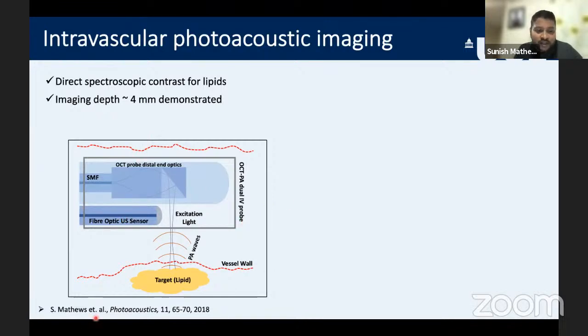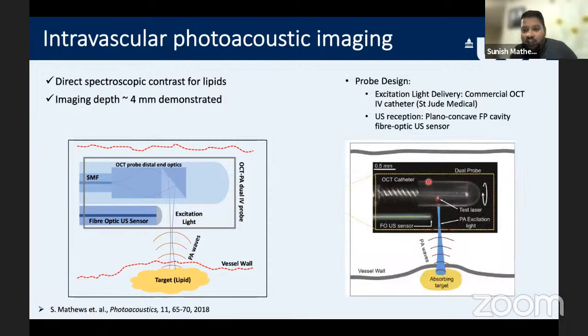So how did we implement this? This is the actual image of our intravascular photoacoustic probe. As I was showing you, this is the optical coherence tomography probe, which is paired with another fiber optic sensor here. The light which we deliver through this optical coherence tomography catheter will then deflect onto the target. The target will absorb, generate a photoacoustic wave, which is detected by the sensor, and that helps to form a circumferential image of the artery. So we are using a commercial OCT catheter, and then we are using our own fiber optic ultrasound sensor.